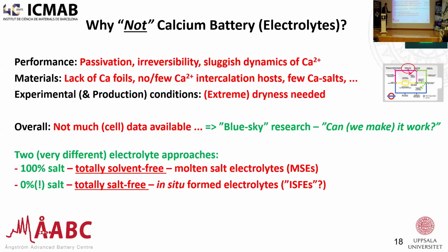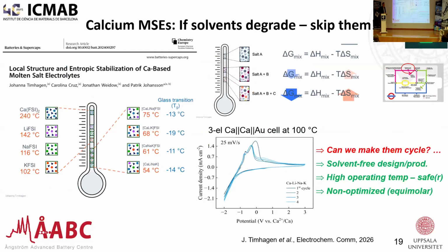And I have tried to give you here now two different electrolyte approaches to calcium batteries. One is that we do a totally solvent-free, just along the lines that I talked about before, 100% salt, very expensive, but exploratory and has some promises. 0% salt, a totally salt-free electrolyte. And then you can say, yeah, it's a crazy guy. Yes, in situ formed electrolytes. And I will bring you to that a little bit in a moment.